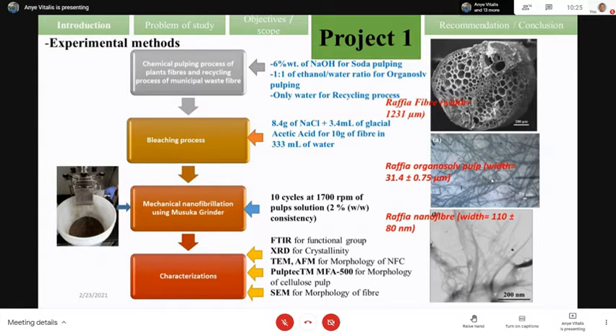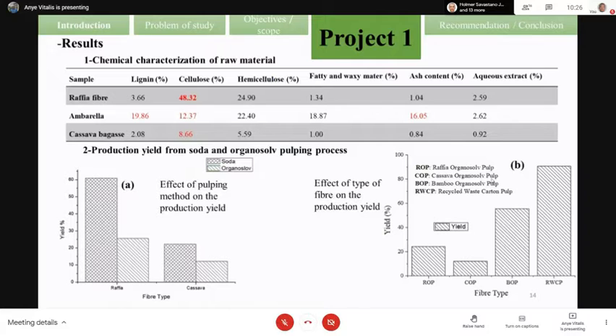It can be seen on the left that from the raffia fiber with a diameter of 1,231 micrometers, we can have, by using organosolv pulping, a fiber with a diameter of around 31.4 micrometers. By using the nanofibrillated cellulose process, we can have a nanofiber with a diameter of around 110 nanometers.